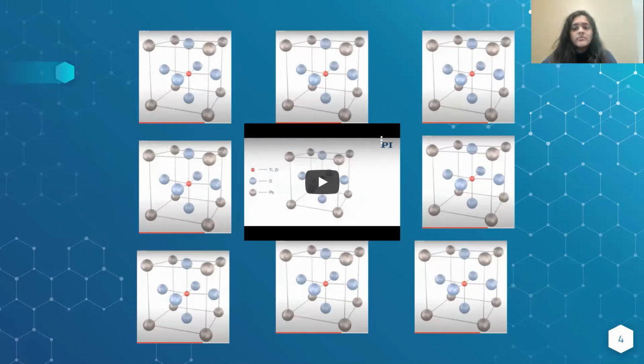It's also important to note that if you strike the crystal, you will generate a temporary voltage that corresponds to the strike, but a constant pressure won't produce a constant current. Something you can see in the diagram here is that you need something like the ion in the middle, which is titanium or zirconium according to this diagram, which moves with force applied. It doesn't necessarily have to be titanium or zirconium, but you need specific properties in the material structure in order for it to be a piezoelectric.